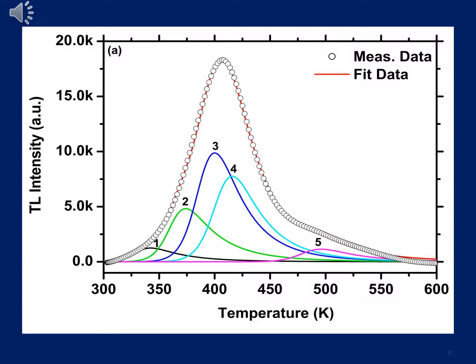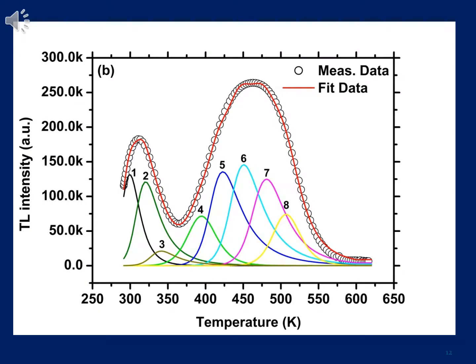Now in this case I have fitted my glow curve to give me several peaks, and to do this I need several other parameters in order to calculate activation energy corresponding to each thermal peak. However, in this case, my interest is not to look into that, but to show the effects of charge compensation in our materials. Now, this would be a material without a charge compensator. Now, let's see what would then happen in the case where we're incorporating charge compensators into our material. And there we are, a material which has been charge compensated. We can clearly see the effects.